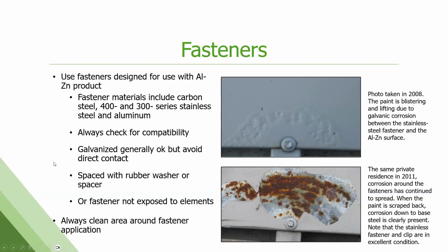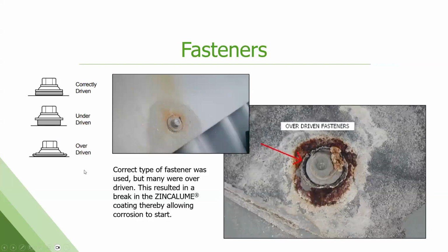Corrosive environment. This is an example of a fastener that was over driven. So it broke through the washer underneath and penetrated and broke that metallic coating underneath on the painted metal. Kind of looks like galvanic corrosion on the surface of it because you're getting this bloom of corrosion underneath the paint. But the root cause is a little bit different, from the fastener being used wrong.